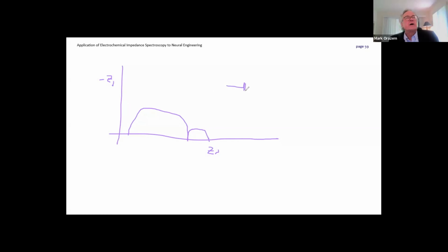And the response I got was that was a very interesting result because this was his dummy cell. And his dummy cell looked like this, which should show 1 capacitive loop, not 2. And so we finally discovered that he had chosen some kind of a low frequency bias reject setting on the instrument. When we turned that setting off, then the second capacitive loop disappeared. So yeah, other things. If you have long cables connecting to your instrument, the capacitance of that cable and the resistance will give you a capacitive loop too. So anyway, I'm just saying, yes, that absolutely can happen.